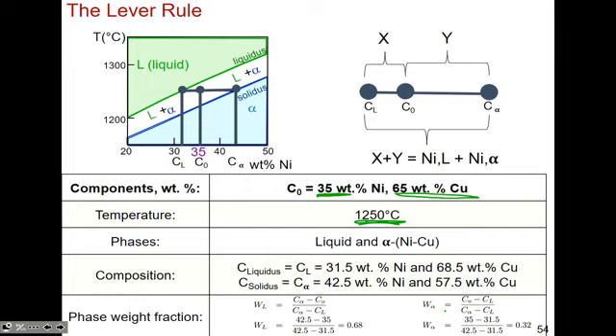So if you set up this table for yourself, you say, I know I have some liquid and solid. My liquidus, here I've actually worked it out to 31.5 weight percent nickel. The composition right at the solidus, if you trace it down, is 42.5. Then the phase weight fraction, how much liquid is in there, is C alpha minus C naught, the composition that we're working with, over the entire length. Here C alpha is 42.5, CL is 31.5, and your C naught is 35. So the total, x plus y, is this length, and the difference is C alpha 42.5 minus 31.5, so that's your entire length.